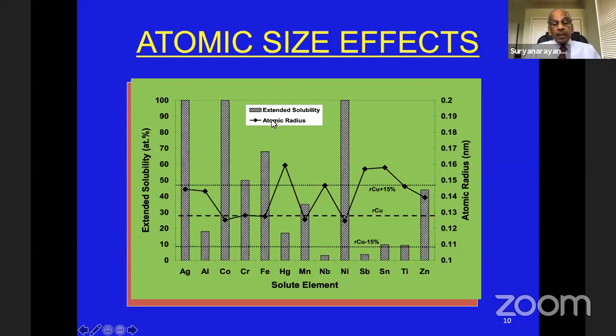The bars here represent the extended solubility limits of the different alloy systems. That means copper-silver, copper-aluminum, copper-cobalt, copper-chromium, copper-mercury, copper-antimony, like that. And the black points represent the atomic radius of these elements. For example, this is the radius of nickel, this is the radius of mercury, this is the radius of cobalt. What you would notice is that the maximum solid solubilities are obtained only when you are in this particular range. The moment you go outside this range, the values seem to be very limited, and you can see that very clearly here. But there are some exceptions, but we will not talk too much about them because we do not have enough time right now.